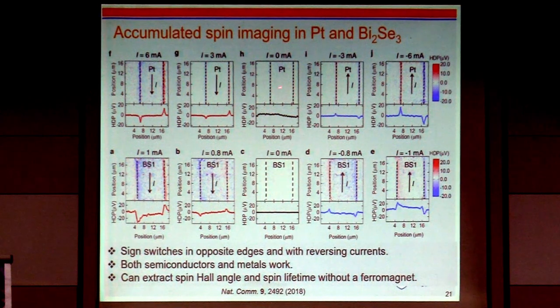So I apply it to platinum. At zero charge current, nothing happened because my injection is zero. As I increase my charge current to 3 and 6, I can clearly see bluish and reddish colors, representing down and up spins accumulated at opposite edges. Once I flip my current, I can see now red and blue, which is exactly opposite. I can easily apply this to a semiconductor, bismuth selenide, which people call a topological insulator. But in my mind, it's a very dirty semiconductor at room temperature. At zero charge current, nothing happened. But as you can see, at 1 milliamp, I can see blue and red. With opposite charge current, it is red and blue, which is exactly opposite.